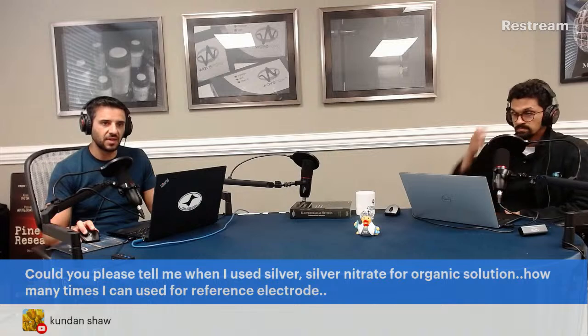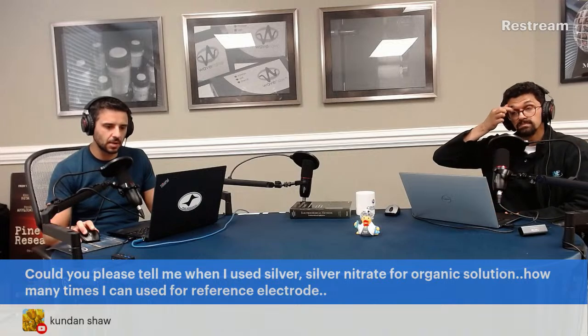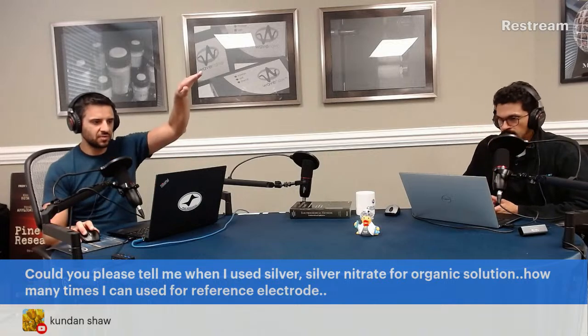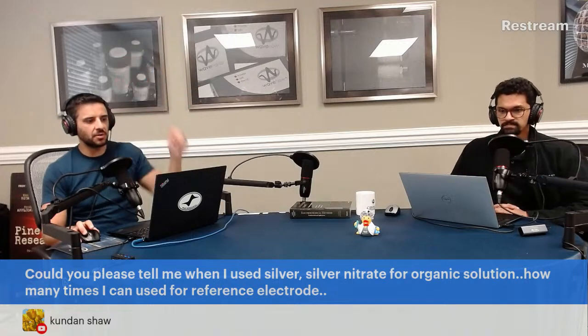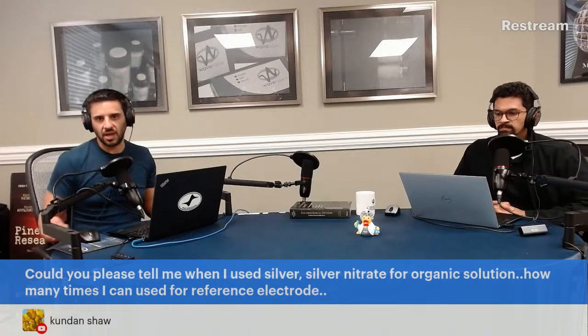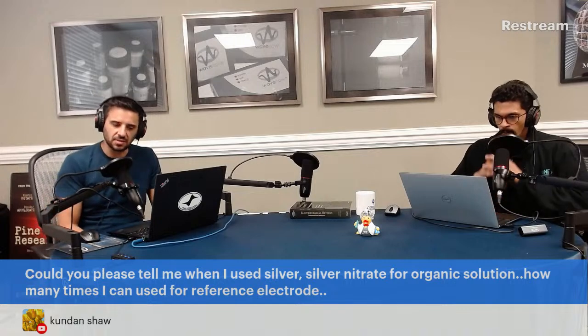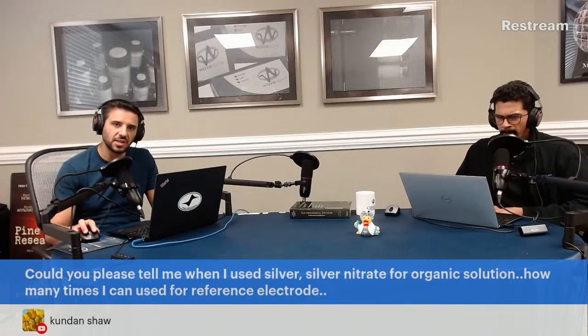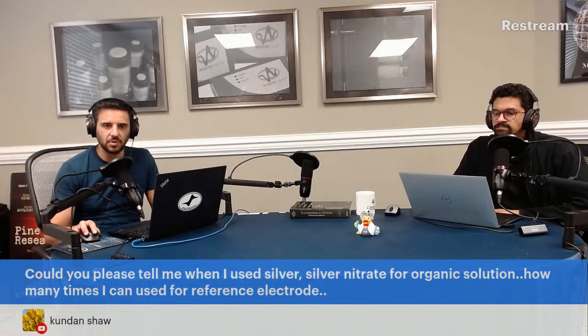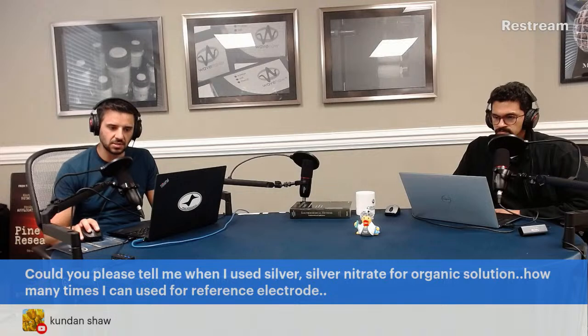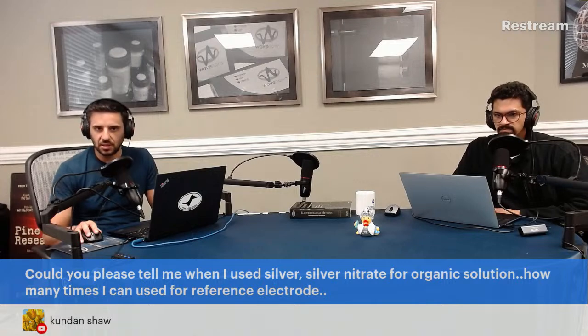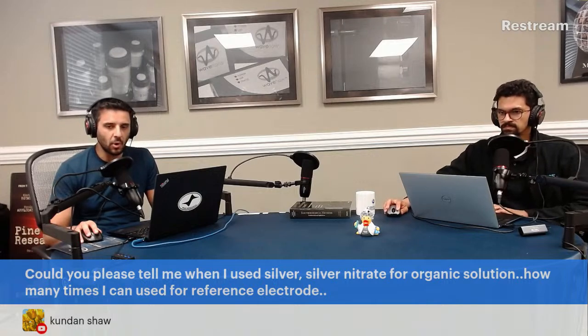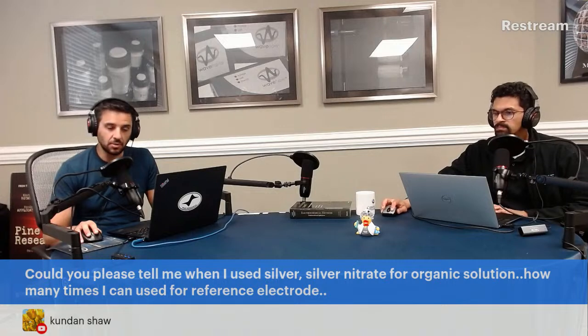Because if you're testing it against a stable reference couple and it's moving constantly or swimming around, going up or down over time, then you can't really know what your reference is in your real system. So you do need to use an internal standard like ferrocene. Some people add a bit of ferrocene if it doesn't interact with their redox system for non-aqueous, right? And you always adjust things to the ferrocene E0 basically after the fact, or you simply don't know.